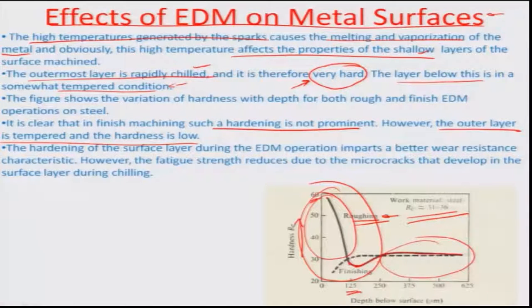So, the hardening of the surface layer during the EDM operation obviously would impart a better wear resistance as far as the roughing process goes, because the hardness changes. However, the overall fatigue strength would reduce due to micro cracks that develop almost always during a rapid chilling process, whether it is a casting process or some kind of heat treatment of a cast or forged material part, etc., that we had discussed earlier in the material properties section.